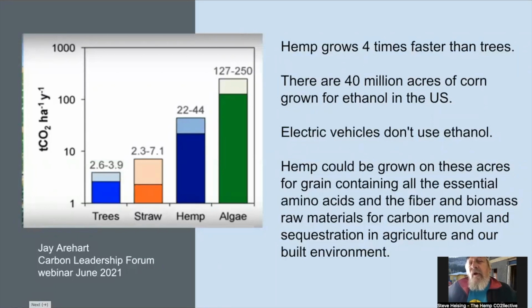So hemp, it grows a lot faster than trees. It grows faster than straw, not as fast as algae, but we can do it on regular cropland. And we can do it with minimal fertilizer, minimal herbicides. And we have something on the order of 30 to 40 million acres of corn now grown for ethanol. And we think in some ways that, considering the land use changes and the disturbance, it's as much as 25% worse for the environment than just burning the gasoline. May not be good for the brown cloud in Denver, but there's enough land to be able to get half a gigaton of hemp carbon removal, and another, by not using fiberglass and not using Tyvek and not using all of the stuff we use now, we could save another 3 times that much in avoided emissions.